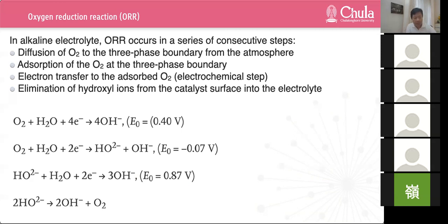And ORR may proceed through the 4-electron pathway, which is the more efficient pathway, or the 2-electron route. For 2 electrons, this process can be denoted as a serial 2 plus 2 electron pathway. And the ORR route depends on the configuration of oxygen adsorption that exists on the active site of the catalyst. The two types of oxygen adsorption are end-on oxygen adsorption and bidentate oxygen adsorption, which lead to the 2-electron route and direct 4-electron pathway.